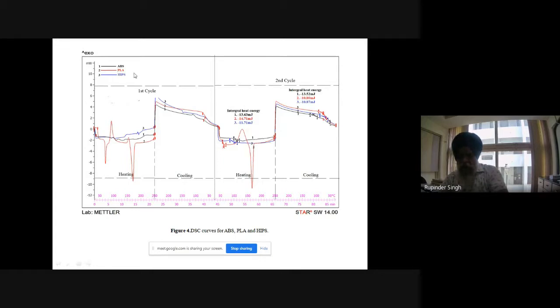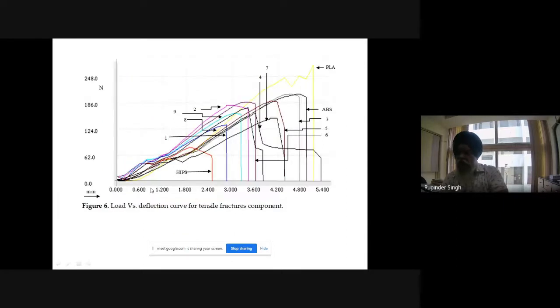So we can take that this material is more or less thermally stable. For PLA, it was taking 14.71, but it was coming out with 10.80, so there is a serious threat to its thermal stability, right? Then HIPS is taking 11.7, and the output in the cooling cycle was 10.8, so it is better than the PLA. So PLA was the least thermally stable material. We tried to see this effect from room temperature to some high temperature. Similarly, we tried to see the stress strain curve, which is important because it shows how this material is going to behave under a particular loading condition.